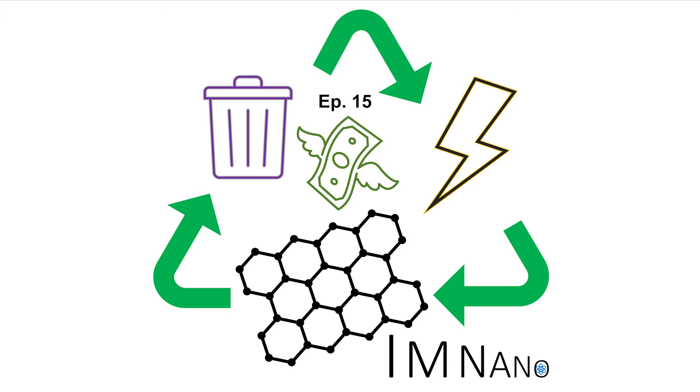We covered that the type of graphene is turbostratic and has messy layers. Let's talk a little bit more about the actual magic — the method. For graphene to commercially be viable, we have to make it in a cheap and fast way, which before flash graphene was not the case, as it cost up to $200 US dollars for one kilogram of graphene depending on quality. It's called flash graphene because it's made in a flash, and it's done by zapping the carbon materials. The method can make graphene from any carbon source without solvents or chemical additives, and you don't even have to do it in a clean room or an inert or argon atmosphere — you can do it out in the open air — to make usable graphene that costs only $100 US dollars per ton, meaning $100 for almost 1,000 kilograms.